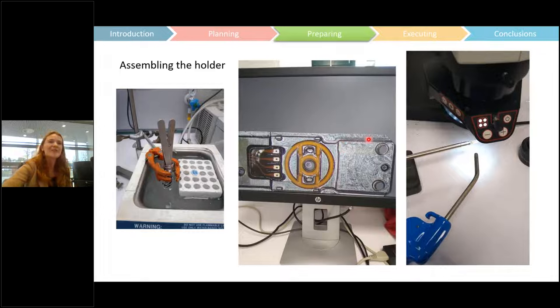I understand that this is going to make people nervous about carbon contamination. We never see the carbon contamination. We give it a quick dry with a spray of air. And if you leave it long enough, it's usually absolutely fine. What you can do if you're really concerned is spray a little bit of air through the ports at the back of the holder so that the air flushes through these ports here. But realistically, we've never really seen a problem from this. We see more problems from having leaks than we do from making sure that our O-ring goes straight onto the holder without any risk of picking up dust or dirt. We find this is a really crucial step for us.